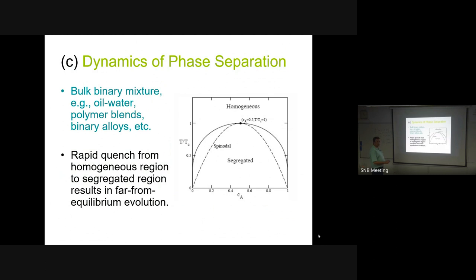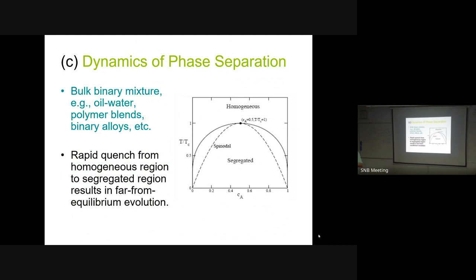The kinetics experiment: start with a homogeneous oil-water mixture, rapidly quench it down, and ask what is the kinetics of phase separation. The model is the Ising model with Kawasaki exchange kinetics - spin +1 means oil, spin -1 means water. When you interchange spins you preserve the number of oil and water components. From a master equation derivation, you end up with the Cahn-Hilliard equation (Model B).